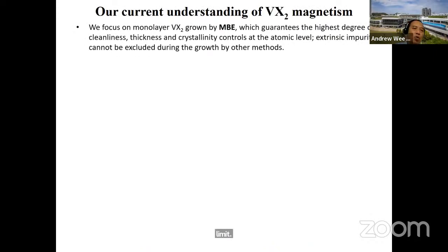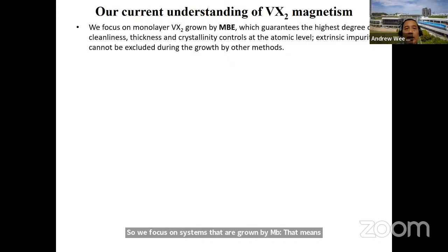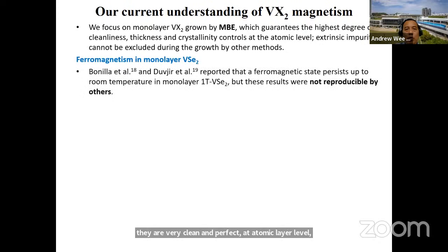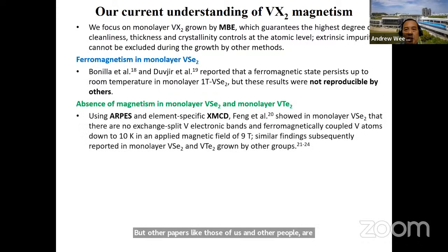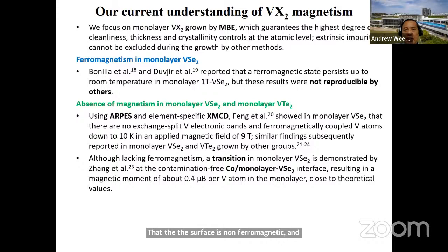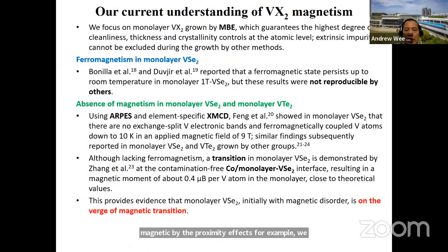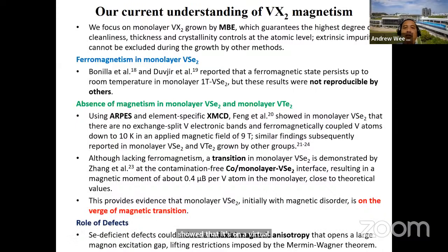Okay, so what do we know about the vanadium dichalcogenide system? So we focus on systems that are grown by MBE. That means they are very clean and perfect at atomic layer level. And several papers, including that in Nature Nanotechnology, showed that they could get room temperature ferromagnetism. But other papers, like those of us and other people as well, showed, especially using XMCD, that the surface is non-ferromagnetic. And although it lacks ferromagnetism, it can easily be made ferromagnetic by the proximity effects, for example, which showed by using cobalt, or by defects. Okay, so we showed that it's on the verge of magnetism, and defects or ferromagnetic impurities can cause a transition to a magnetized surface.